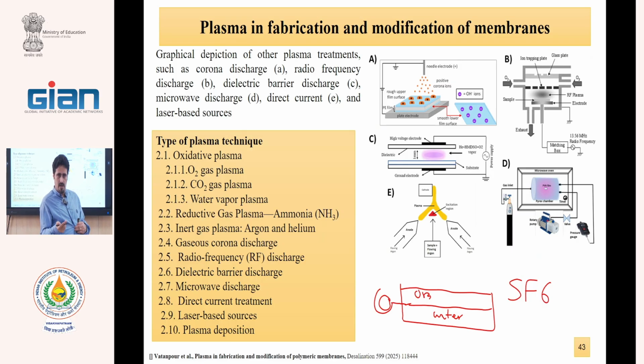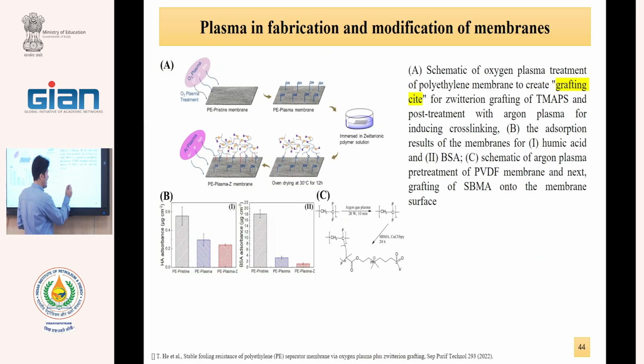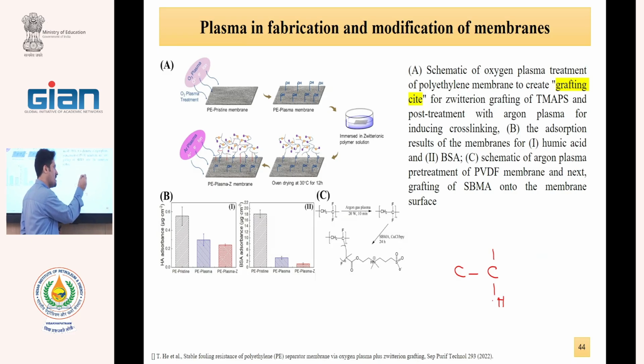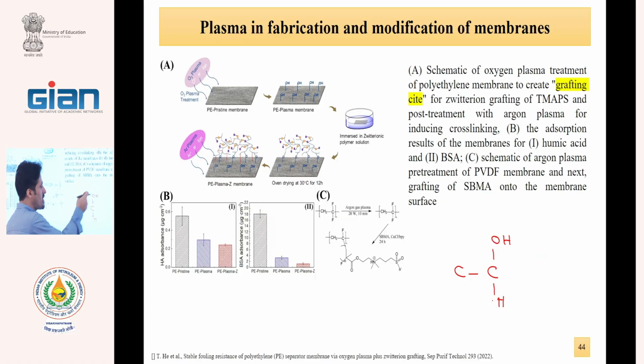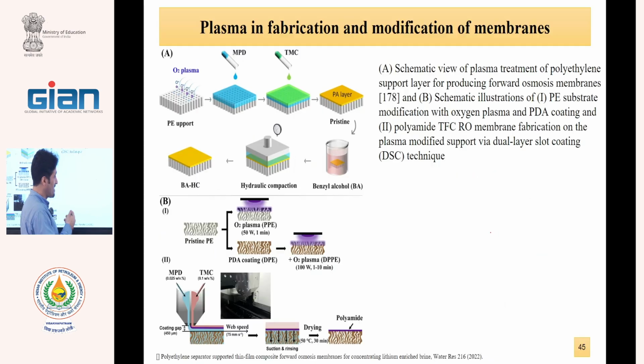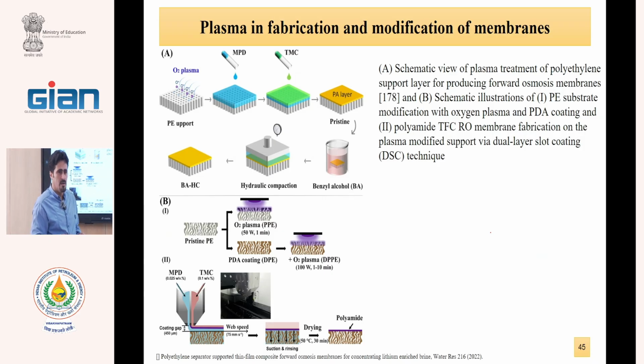How does the hydrophilicity change with chemical function? In polyethylene, we have only carbon and hydrogen groups, okay? When we oxidize this polyethylene, that means we add oxygen groups. With addition of this oxygen group, the hydrophilicity improves, because these electrons can interact with water and can absorb the water and therefore increase the hydrophilicity.